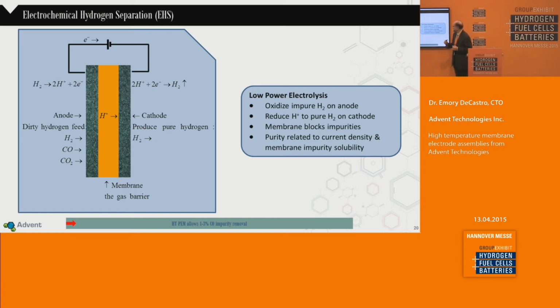And on the left, on the anode side, you feed what we call dirty hydrogen. It could be the output of an anode gas from a fuel cell, but it contains hydrogen, carbon monoxide, carbon dioxide. You actually oxidize the hydrogen. Protons go through the high temperature membrane. You reduce those at the cathode, producing pure hydrogen. Since the solubility of the impurities, which is carbon monoxide, carbon dioxide in this case, is limited to their solubility in phosphoric acid, it's very low. And if you can operate at very high currents, you can actually produce a high relative concentration of hydrogen compared to the small amount of impurities that would still come through the membrane. And so you can actually purify hydrogen using this electrolytic technique, starting with impure hydrogen.